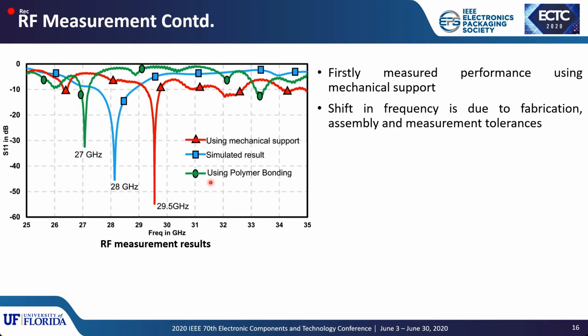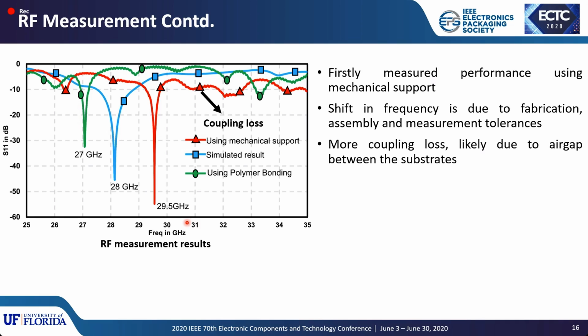So using the mechanical support, the performance of the antenna is measured. As you can see, the measured resonance frequency of the antenna is close to 29.5 gigahertz using the mechanical support. And this shift in frequency is most likely due to the fabrication or assembly or measurement tolerances. And also it is important to note that there is a huge coupling loss in this structure, which is most likely due to a very small air gap between both the substrates.